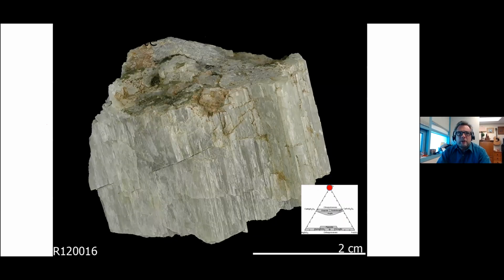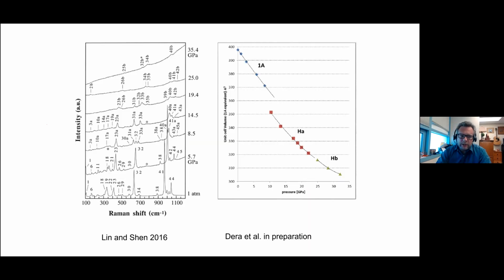In our exploration of the chemical complexity of pyroxenes, we also looked at compositions in the pyroxenoid range of this phase diagram. So we looked at wollastonite, which is the calcium end member. The structure here is a little bit lower in symmetry. Wollastonite has several different polymorphs. We focused on the triclinic polymorph, which is called a 1A phase.